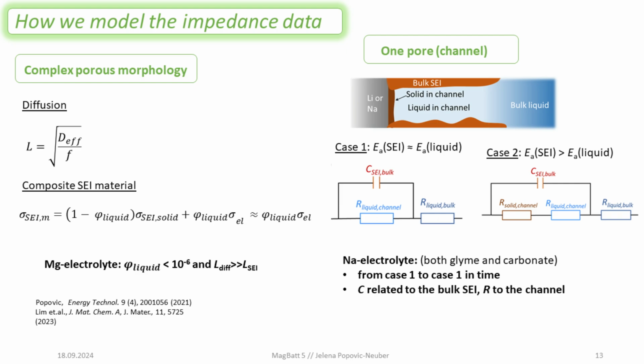In the sodium electrolyte, we see really the switch from one case to the other. But what is important in these kind of equivalent circuit models is, as you see in red, the capacitance actually comes from the bulk. And this is also one of the reasons why this capacitance was off in these Aurbach papers in the mid-90s. So in that case, the capacitance was really not fitting to what we were expecting. But if we just take into account this porous bulk, then this is fine.